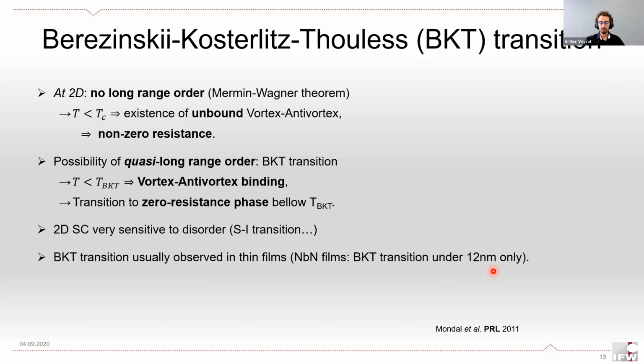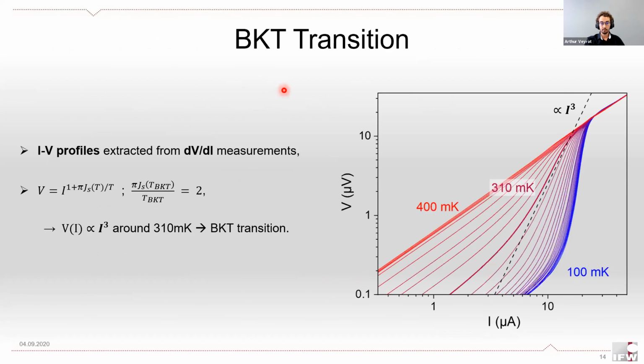So our sample is quite thicker than this, but we still looked at whether we could see some signs of a BKT transition. The easiest thing to do is to look at the current versus potential profiles plotted in a log-log graph. At high temperature, we expect to see a linear behavior, simply the ohmic regime. At very low temperature, we expect to see more of a power law as we have superconductivity.